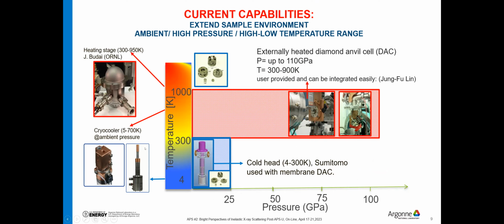This ARS cryocooler has become a standard setup at the beamline for most of the experiments. We can also access high pressure up to about 100 GPa and high temperature by using an externally heated diamond anvil cell. High pressure and low temperature experiments can also be done by using the cold head from Sumitomo together with the membrane diamond anvil cell.